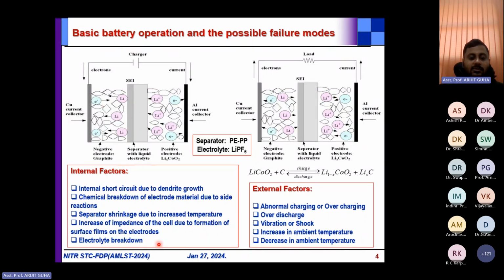Also there can be electrolyte breakdown, which is the breakdown of the electrolyte inside the battery cell. There can be external factors, maybe due to overcharging or abnormal charging. Like if we keep the mobile phone overnight, that will tend to overcharge the battery. Even if it has reached 100%, you are forcefully keeping it for extended hours, and eventually that may degrade the battery, and after some time the usability of that battery may degrade and you may have to replace it. Over discharge is also another mechanism by which a battery can fail. Vibration or shock is also one more reason.